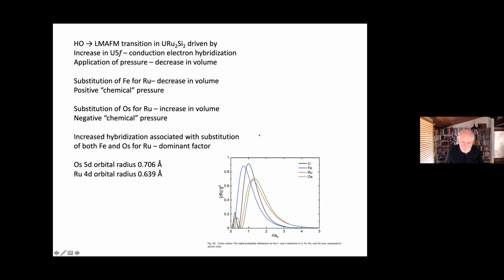Okay, so Peter Riseborough did some calculations, and based on what he did, we would conclude, as I mentioned in the beginning, that really the iron and osmium have stronger hybridization with respect to the 5f states of uranium, and ruthenium is suppressed. And so this then we believe is the real mechanism that is driving this transition. I mean, it is of course due to hybridization, but it doesn't appear to be traceable strongly to the positive or negative chemical pressures. Of course they contribute something, but the dominant mechanism appears to be the simple replacement of these atoms with stronger hybridization than ruthenium when you make these two substitutions.